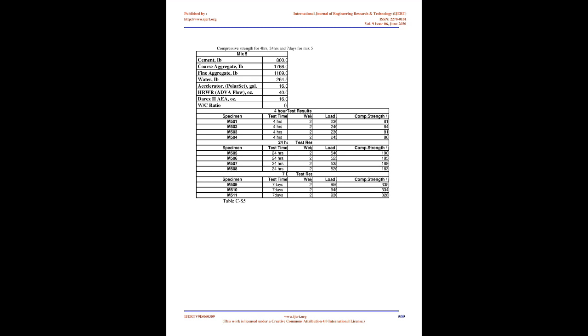The mixes employed in this research were designed to attain a compressive strength of at least 17.5 MPa in 4 hours or less. It was also expected that the mixes would go through at least 300 cycles of freeze and thaw without failing or excessive scaling. A summary of the test results is discussed in the sections that follow. 4.1.0 Properties of the concrete mixes. The property of a concrete mix depicts its strength, durability, and performance under loading. Properties affecting concrete characteristics measured in this research include the following.